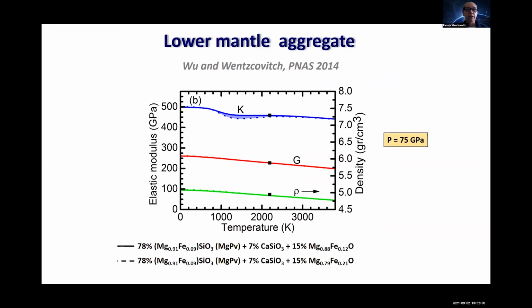So here is a prediction of, essentially, is this softening of the bulk modulus that we see observed in the mantle? Well, this is a complex question, and one way to address this is to look at velocity heterogeneities, because this spin transition has a remarkable effect on heterogeneities. If you are at 75 GPa and you plot the bulk modulus of the pyrolite aggregate as a function of temperature, what you see is that when you go across the mixed spin state, the bulk modulus softens, and the shear modulus doesn't change very much. So there is a region in the mantle where you have an anticorrelation between dlnVs/dT and dlnVp/dT.